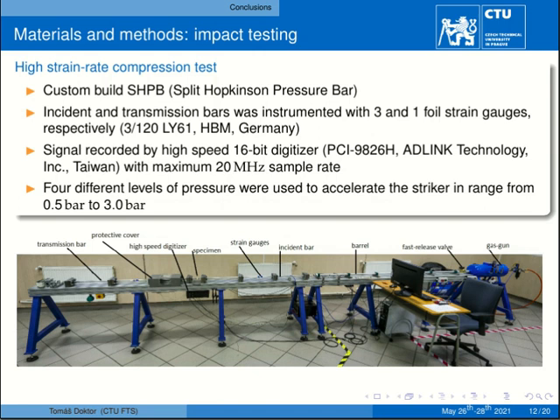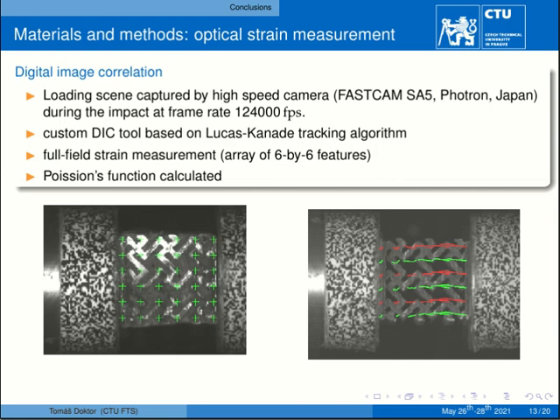of the deforming sample. The strains at the surface of the deforming sample were evaluated from the obtained images from the high-speed camera using a custom digital image correlation tool based on the Lucas-Kanade tracking algorithm. Using this tool, a full field strain measurement was performed from an array of 6x6 features on the surface of each sample, and from these displacements obtained by digital image correlation, the Poisson's functions were then evaluated. For each sample, the dependency between the Poisson's ratio and longitudinal strain was then obtained.